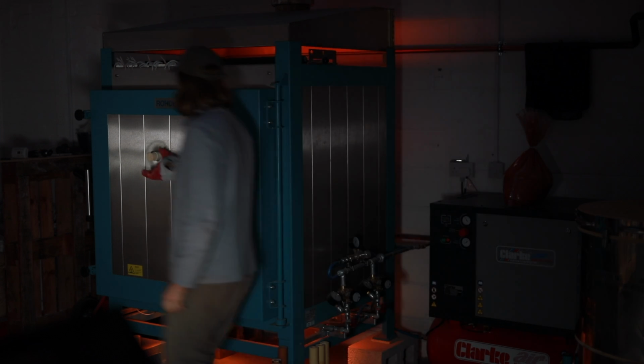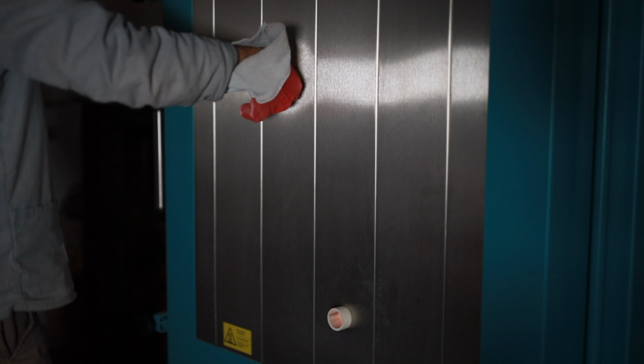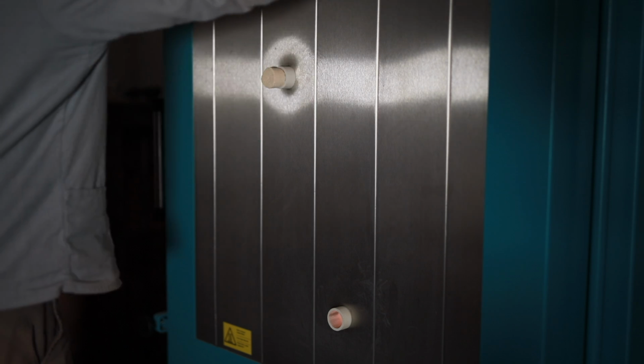I then crash cool the kiln from 1295 degrees back down to 1000 degrees, and I do this by opening the flue up fully and by pulling out the 2 spy holes on the front of the door. This process helps the glazes maintain their colour and also stops it from overfiring, as it can potentially keep rising just at the moment you turn it off. And finally, I can close the dampers fully, and I can also put the bungs back into the spy holes.